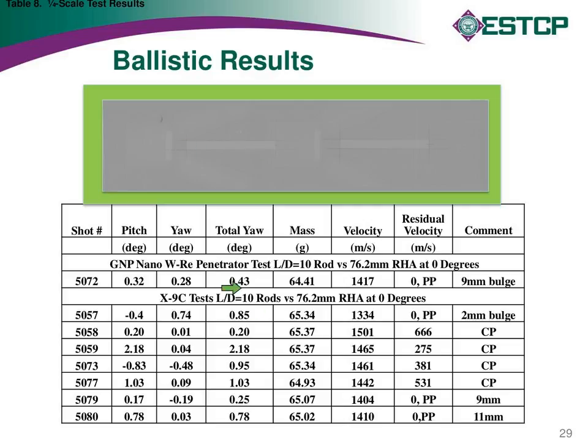Our measure of the total pitch and yaw at impact was less than half a degree. 0.43 is the number we came up with. So good impact. The velocity was close to where we wanted it: 1417. If it had gotten through at that point, we would have been sure that we had a material that was better than a conventional tungsten heavy alloy of the same density. This material was about 18.5, almost 18.6 in density.